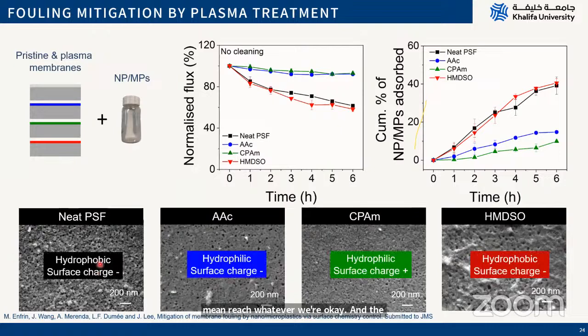Just to clarify, this first membrane, the pristine one, is relatively hydrophobic and has a negative charge. The acrylic acid is relatively hydrophilic, but also has a negative charge. The CPAM is very hydrophilic and has a positive charge, and the HMDSO is very hydrophobic and also has a negative charge. So you can see the relationships, which make sense across this series.